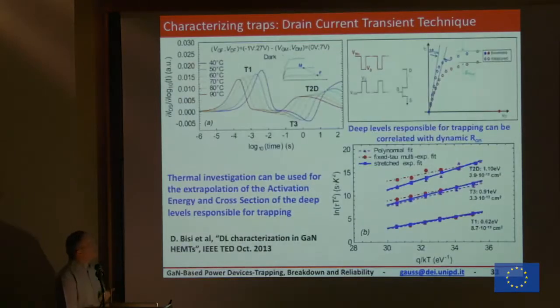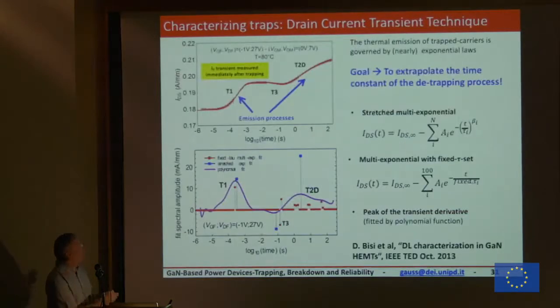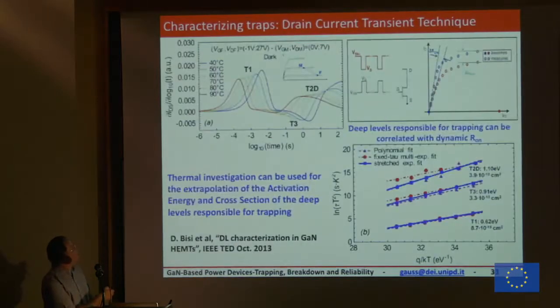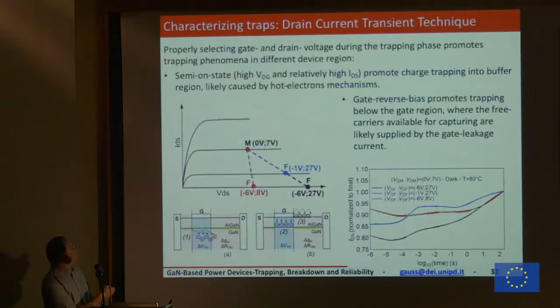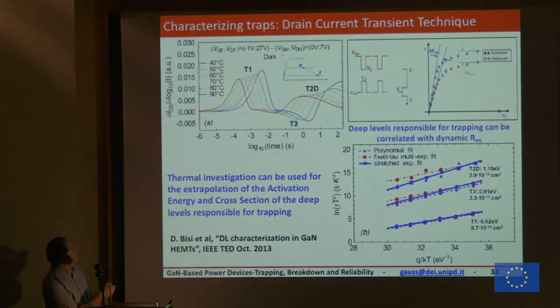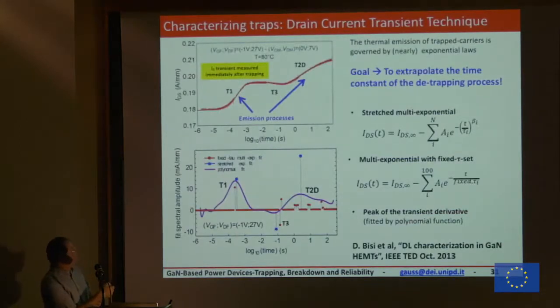Important point. Second point, I can do, for instance, for one kind of trap, measurements at different temperatures. What typically I do, because it's much easier, is to identify the time constant of these traps. I can see something between 10 to the minus 4 and 10 to the minus 3. But if I do the derivative, so first I do a better fitting, then I do the derivative, I may end up with this plot. And it is much easier for me to identify the time constant of the traps as the peak of this derivative. That is, in principle, the place where we have the largest slope of this curve.